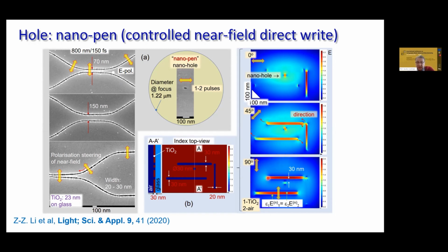So you see light is very happy inside the groove. It's high intensity, but this nano feature here has some light localization, but also has depression nearby. So if you use this spot to write your modification of the surface, you can write very closely to something already existing and fabricated, and you will not damage it. So this is a really unique way of modifying surfaces,